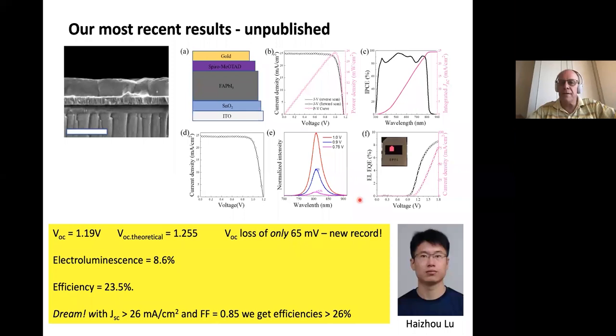It's this measurement here, where you see the light here. Now, let me just finish a little bit by dreaming. Our efficiency here at best is 23.5%. The record we have is the voltage. We are losing a little bit in the current, but let's take current values which are published, combine it with, well, I would say this is a stretch, but people have seen such high fill factors, together with the voltage we measure here, we are getting higher than 26%. So I think that can be possible. I put it as a dream, but I wouldn't be surprised that we see something like that from someone in the near future.